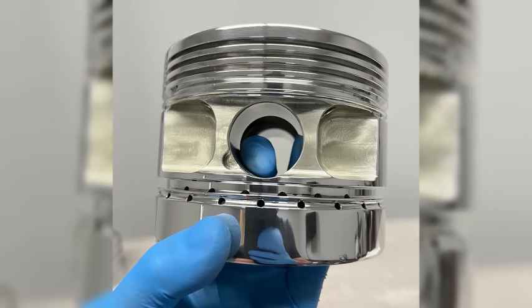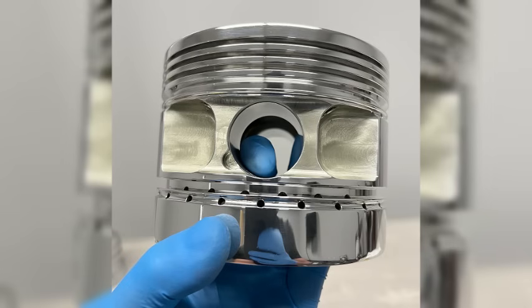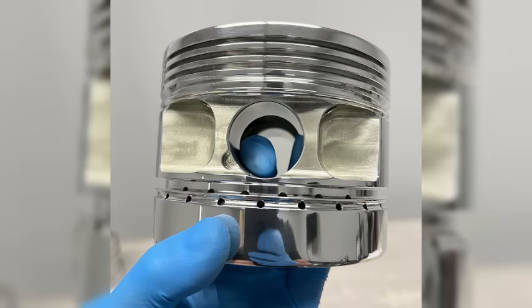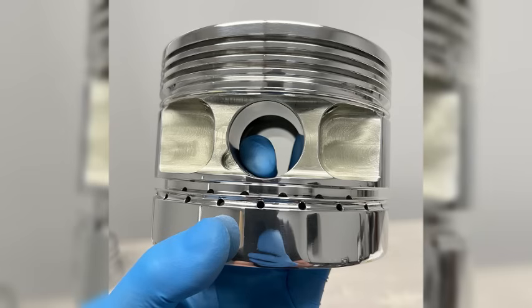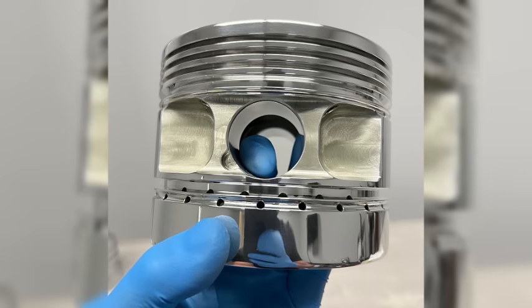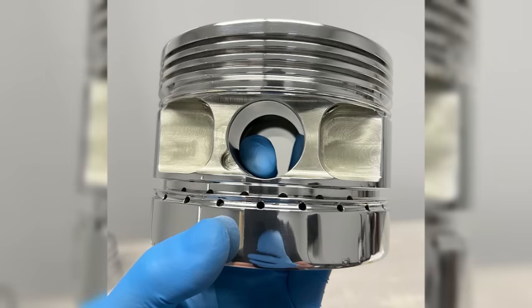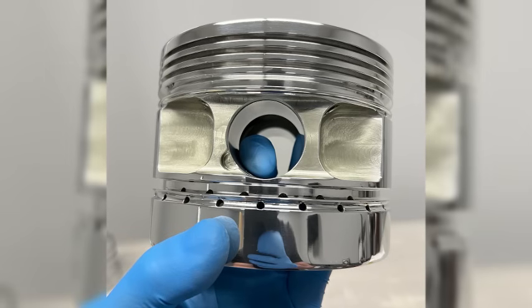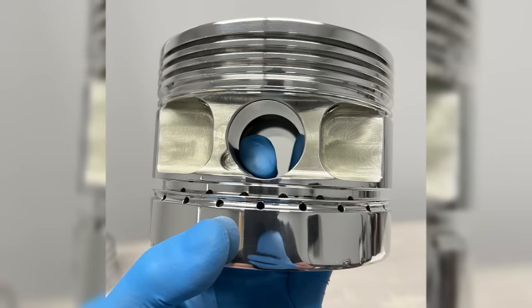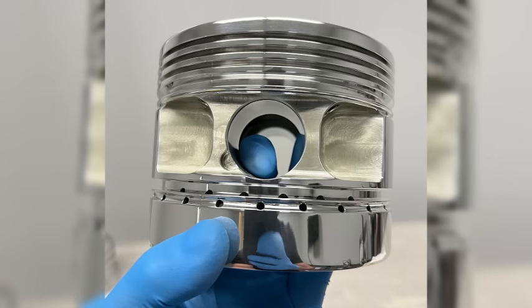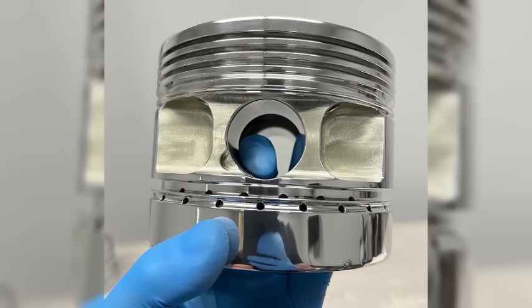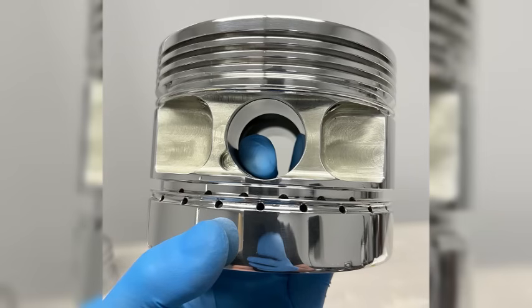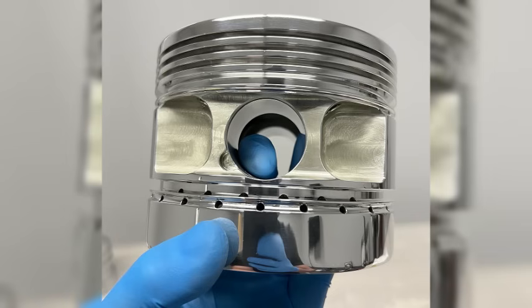The results surprised everyone. Chrome-plated rings not only matched British rings, they exceeded them in some measures. Wear rates were lower. Oil consumption was reduced. The rings maintained tension and sealing over longer periods. After 100 hours, Packard engineers tore down test engines and examined the cylinders. Wear was minimal, barely measurable. The chrome surfaces showed polishing but no significant material loss. After 200 hours, results were similar. After 300 hours, approaching the overhaul interval for combat engines, the chrome rings still showed excellent condition.